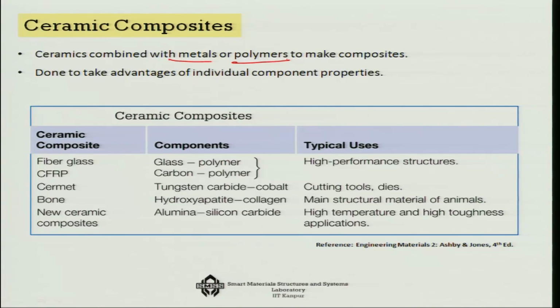In ceramic composites, fiberglass is one of the important examples, which is a composite of glass and polymer used for high performance structures. CFRP has carbon again as a reinforcement in the polymer. Cermet: tungsten carbide is used with cobalt, and that is used in cutting tools. Bone, our human bone, is one of the best examples of ceramic composites, where you have collagen fibers. Collagen here works like a fiber, and hydroxyapatite works like a matrix. There are many new ceramic composites coming up, like alumina silicon carbide, which has high temperature and high toughness applications.